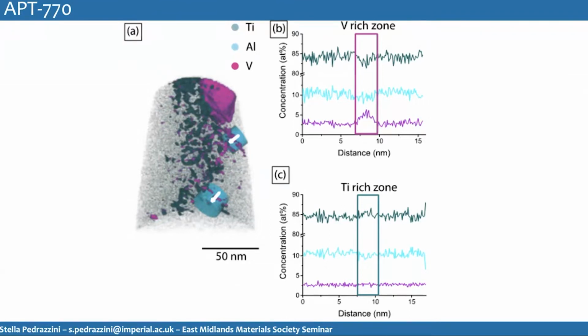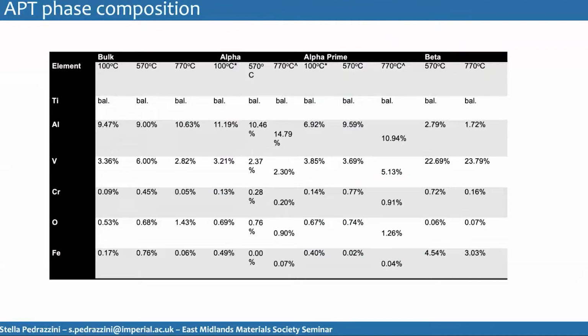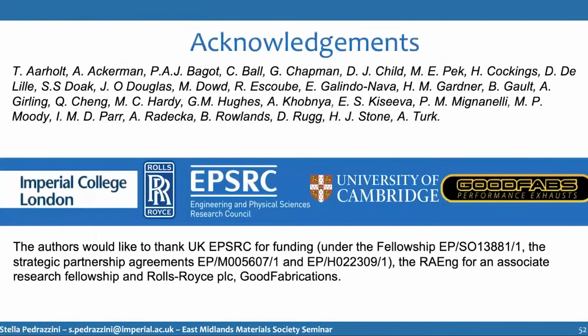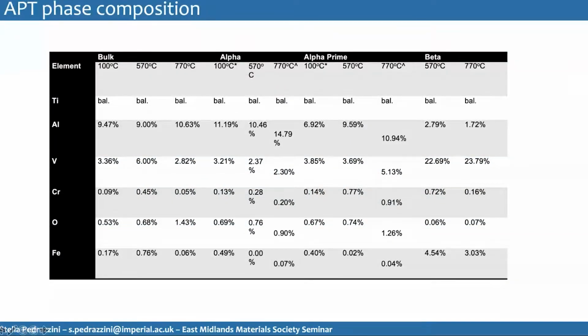So in this case, we can tell that at 100 degrees the overall oxygen content is quite high, but at 100 degrees and 570, there's still ductility, and at 770 there isn't. So there's clearly a different mechanism that's causing the embrittlement. And it's interesting that at 100 degrees, the stresses from 3D printing manifest in twins, that then at 570 are no longer present, but then there is a very high dislocation density, and the dislocations contain a high vanadium content, but no particular oxygen content. And then at 770, these dislocations no longer look like they're mobile. So this is the conclusion that we've reached from this study.